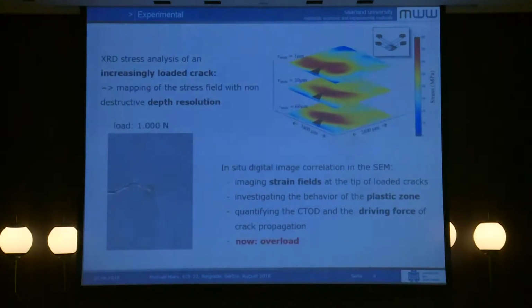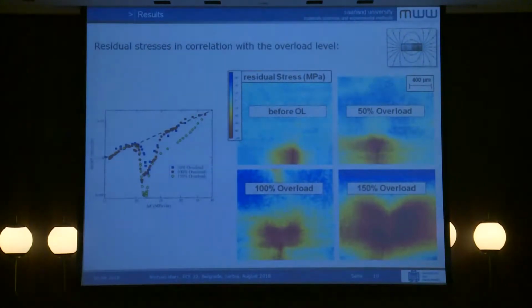And then we come to the overload. This is a 50% overload. And here we have a 100% overload with a quite huge crack tip opening, and from this we can then also calculate our strain field by the digital image correlation. So now here are the results. This I have shown before.